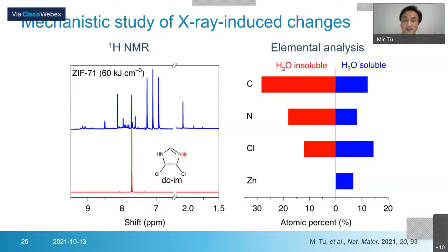So this linker is being damaged, and maybe there are many other reactions involved. So it has many different products in the system after X-ray exposure. Then we also did some elemental analysis. If you remember, we mentioned before that after X-ray exposure, these MOFs are partially soluble in water. So we did elemental analysis on the water soluble part. It has zinc, and all these three elements. And interestingly, the water insoluble part doesn't have any zinc, and it has a lot of carbon. So we propose that after X-ray exposure, it has oligomers or polymers, which are not soluble in water but soluble in DMSO. And the water soluble part may have some zinc nitrogen coordination complex.